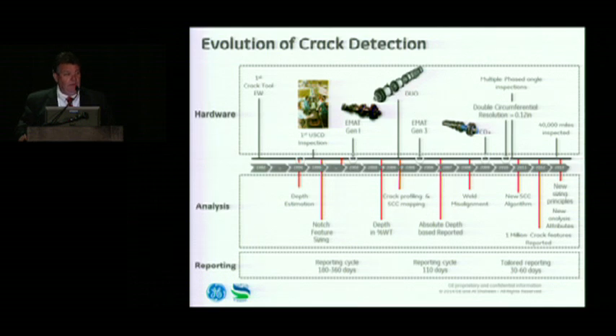Then the gas operators got a bit upset because this really served the liquid market. And we needed something for gas, so the EMAT tool was designed back in 2002, the original generation. But it fell into the same problems the Elastic Wave had, and that was it couldn't discriminate between SCC colonies and laminations, or stable features, or whatever we're going to call them now. Basically, defects that you don't want to be digging up. So we came up with a generation 3. We put another sensor on the tool to discriminate the difference between laminations and corrosion and real cracks. And that's been very successful ever since.